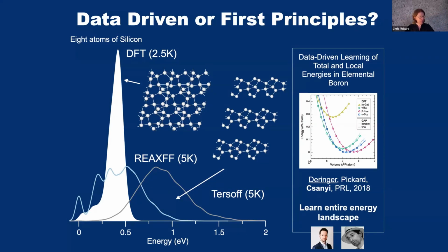But actually, my mind has been dramatically changed by my work with Gabor Csányi in Cambridge and Volker Deringer, where we returned to this problem of developing empirical potentials, but did it in a way that was appropriate for random structure searching. This meant making sure your machine learning potential for your system could describe the entire energy landscape, including the crazy structures that you start off with in a random search.